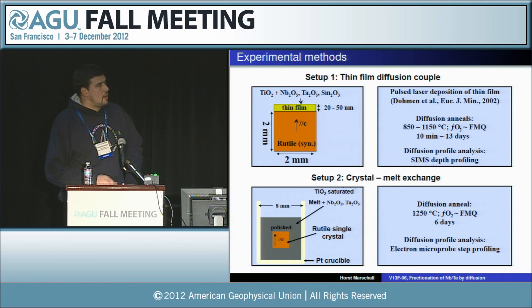So the experiments are two different types, completely unrelated. The first type is single crystal rutile, where we deposit the diffusion source, so something like titanium oxide doped with niobium and tantalum, and those are annealed in a gas mixing oven at reducing conditions at a very large range of temperatures. So we're doing experiments between 850 and 1150 degrees C. And then that is analyzed with SIMS in the depth profiling mode. So you're drilling down your SIMS spot into the crystal, and you can then determine the diffusivity.